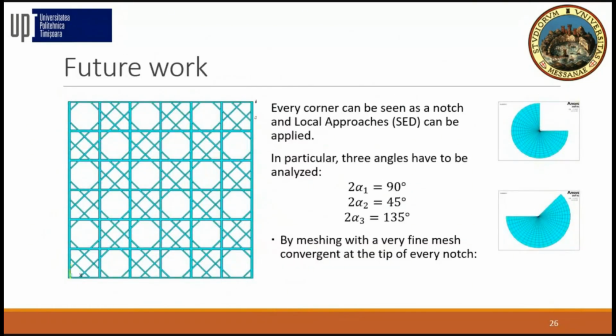What we want to do going further is to analyze locally what happens, to apply the strain energy density approach, because in particular for this structure, we have different angles here: 90 degree, 45 degree here, 135 degree, and 90 degree here. What we need is more experimental data to have the tensile strength and the fracture toughness determined under the same manufacturing conditions of the lattice structure. We are running now another set of tests with another resin, and we also employ digital image correlation for this.